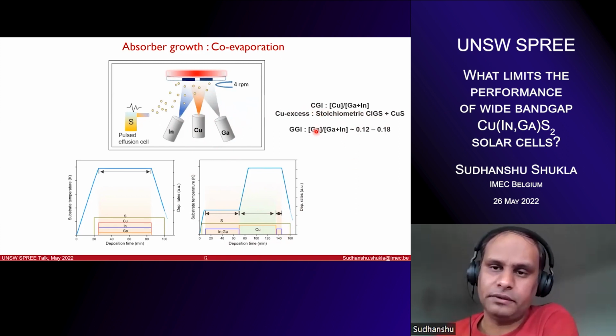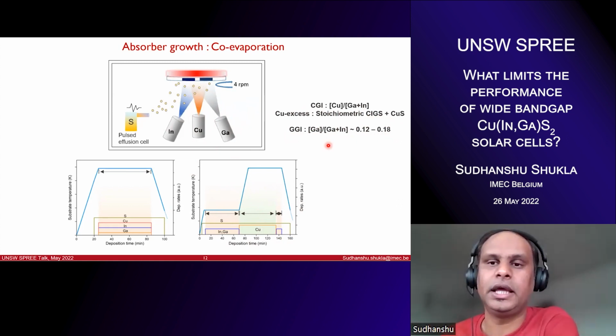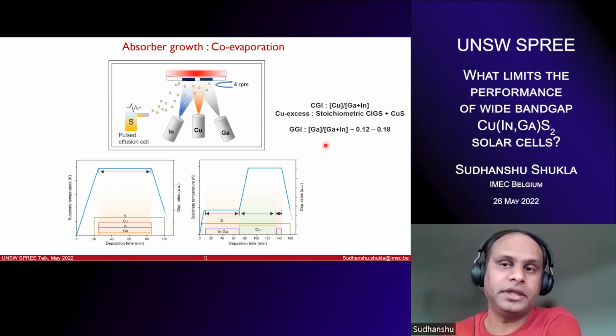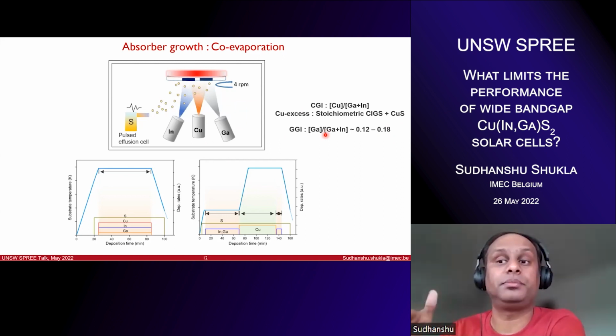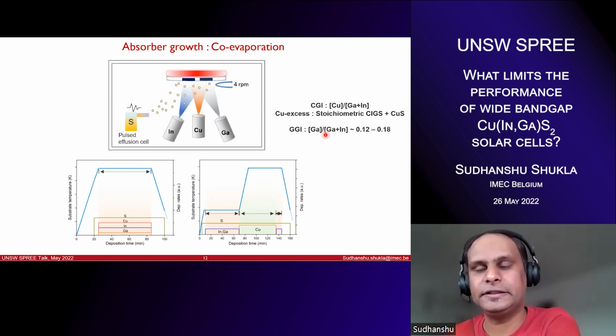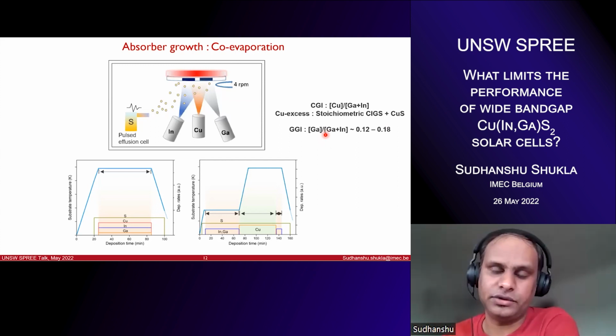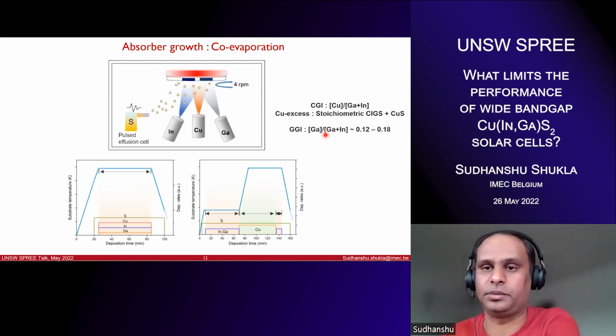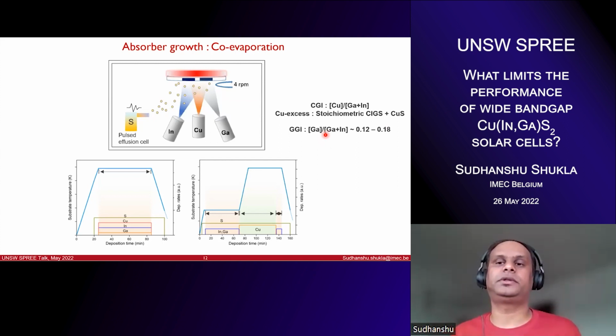All the films that I will show today will have GGIs in the range of 0.12 to 0.18, so exactly in the range where you can make 1.6 eV band gap absorbers. I also want to highlight that when I say copper excess, it's not copper rich CIGS, it is CIGS plus copper sulfide that phase segregates. Then you etch it away using KCN to get stoichiometric absorbers. So all the CGI numbers refer to the absorber as made. There was no etching, meaning it refers to the amount of copper sulfide in it.